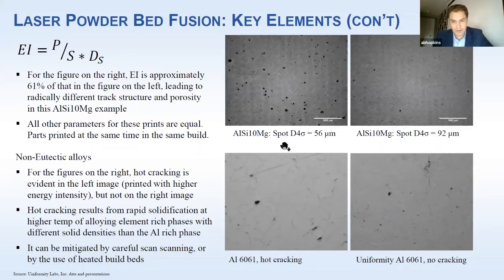And here's what happens. So if you have this spot D4 sigma 56 microns, it's this regime where we're getting that supersaturated hydrogen migration into the melt pool, and it's being trapped. And then if we change the spot, all of the parameters identical, to 92 microns, so just a little bit of a change in spot diameter, you can see you get rid of most of the hydrogen porosity because the length scales and the time scales are not proper for the retaining of that hydrogen in this particular case. All right, great.